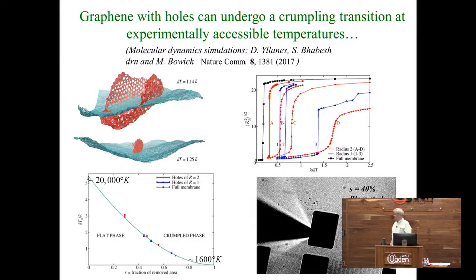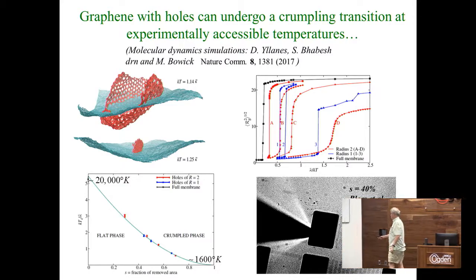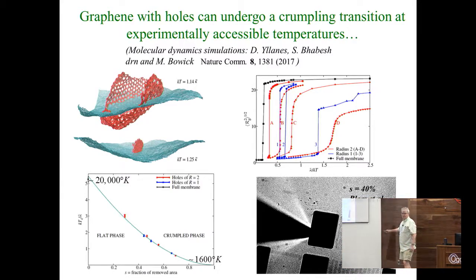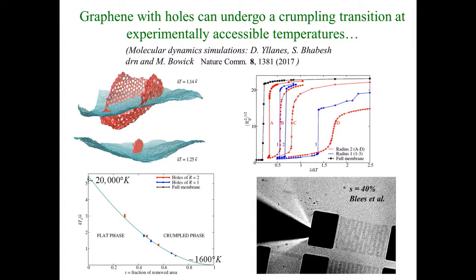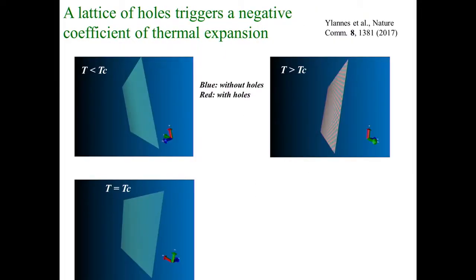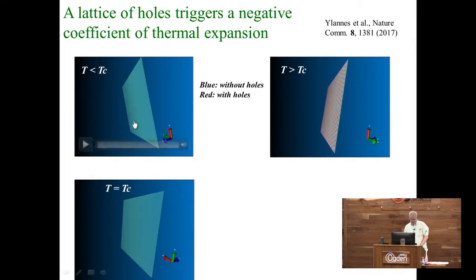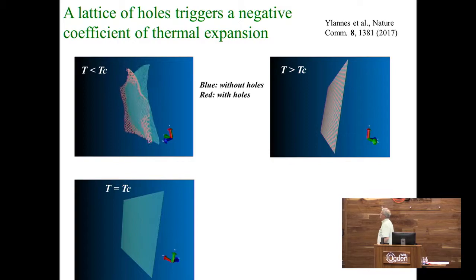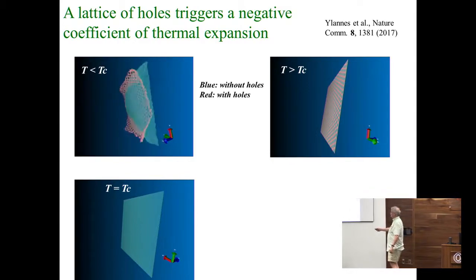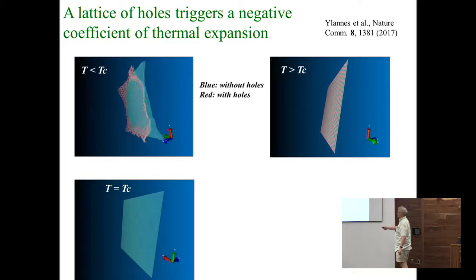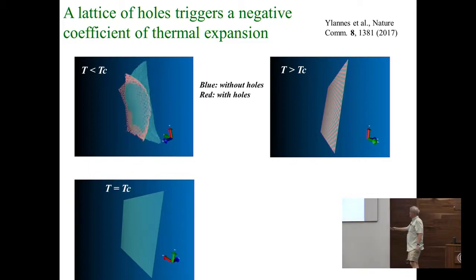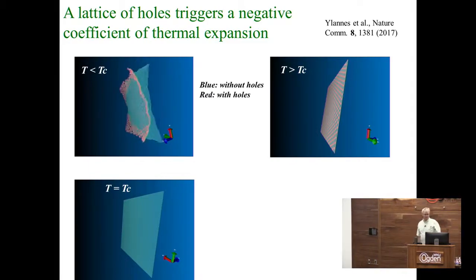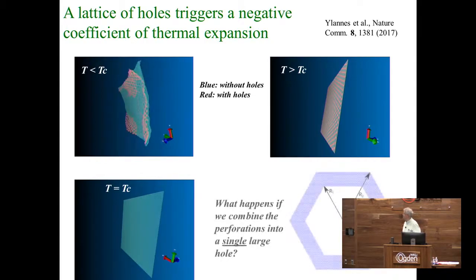So I remind you that we want 85% of the material removed. They've already removed 40% with this graphene spring. But I still haven't persuaded Paul McEuen to do the experiment. But we have done these cool simulations. So here's a simulation where the blue is no holes, the red is whatever it is, 70% or 60% of the material removed. And you can see it's a lot floppier. This is below the crumpling transition. TC stands for T crumpling. Whoops, sorry.